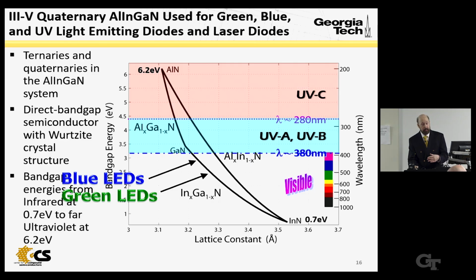And so you have a substrate that's fairly large area. In fact, 12-inch sapphire exists today for green LEDs, blue LEDs, and UV LEDs. And more recently, we have bulk aluminum nitride substrates and bulk gallium nitride substrates to use for this technology.